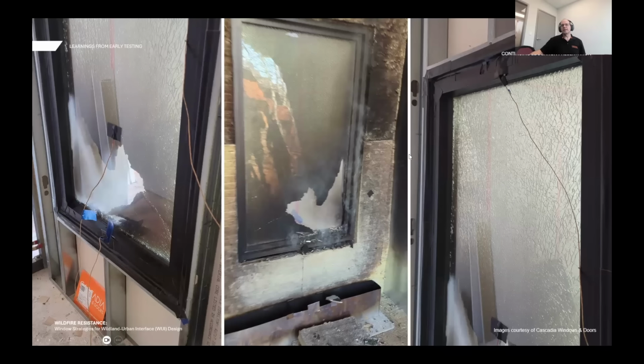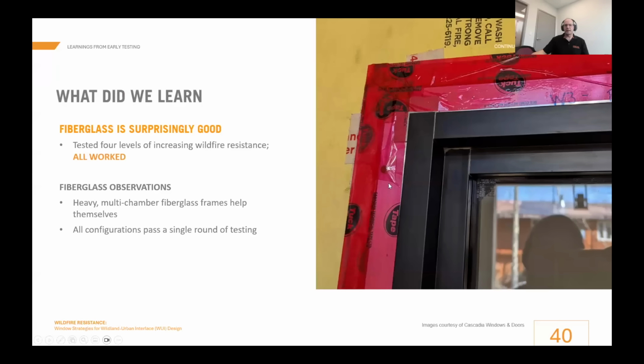But we worried, just like making observations as the 8 minutes dragged on, that if 80% of the glass fell out, would the inner pane have survived? Maybe. But if the test went 10 minutes instead of 8 minutes, would it still survive? I don't know. Maybe not. That's why we think there's a variable there, and we're recommending anneal glass unless you need to temper it for other purposes like safety glass on the door.